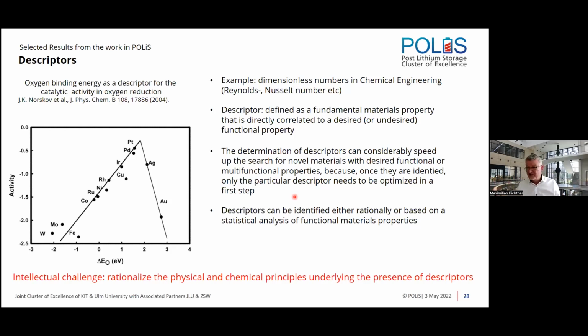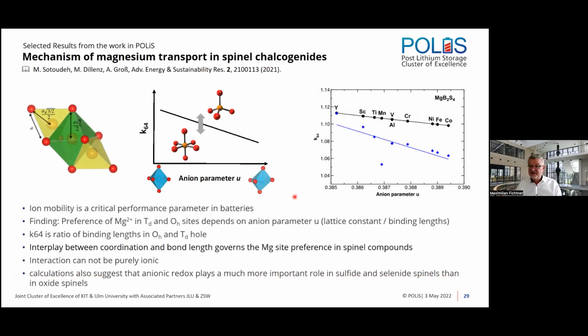Okay, the intellectual challenge now is to rationalize the physical and chemical principles that are underlying the presence of descriptors. And here's just one example. This is, I would say, the first part of this descriptor study, which deals with the mechanism of magnesium transport in spinel chalcogenides. As we have heard, and as we know, the ionic mobility is a critical parameter in such systems. And what was found by Axel Groß and M. Sotoudeh in their theoretical study was that there's a preference of magnesium ions in tetrahedral and octahedral holes, depending on the so-called anion parameter.